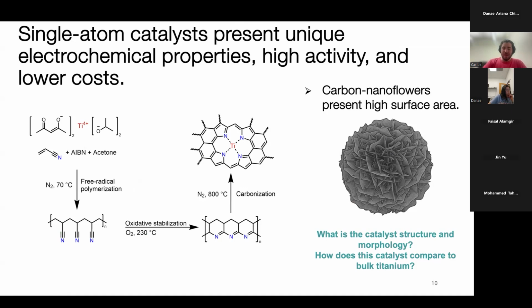But the benefit of this is that titanium creates single sites where we can have a very controlled reaction. So they have a very unique structure and activity for this specific reaction. And then the carbon nanoflower architecture creates a very high surface area nanoparticle that we can use for this reaction as well. So the 2 questions that we have here are: what is the catalyst structure and morphology, and how do these catalysts compare to bulk titanium?